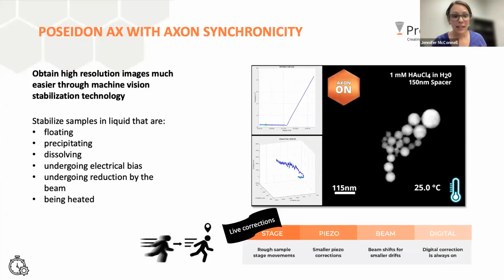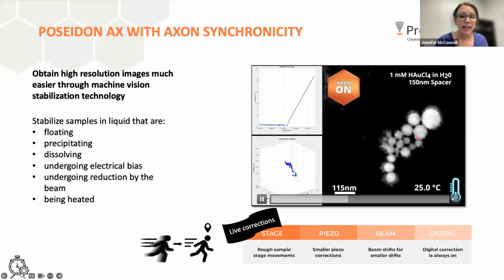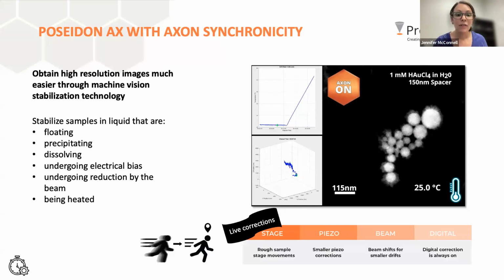So an example in liquid, no matter what your sample is doing, here we've got, let me pause it for a second just to explain. Here we've got some gold particles in a gold chloride solution, and we're going to use the beam to initiate dendritic growth of gold on these seed particles. And then we start heating to exacerbate the growth.